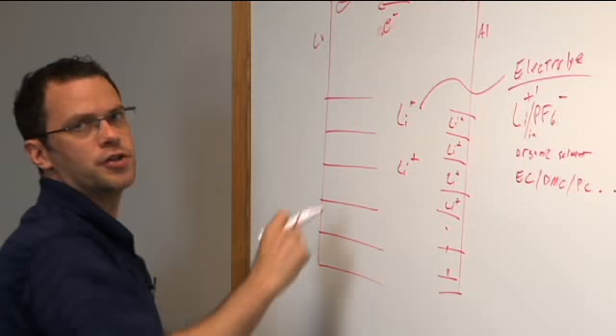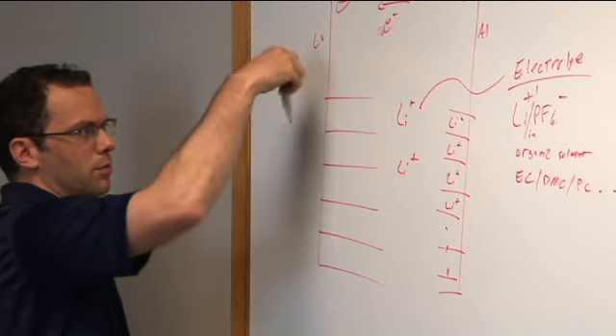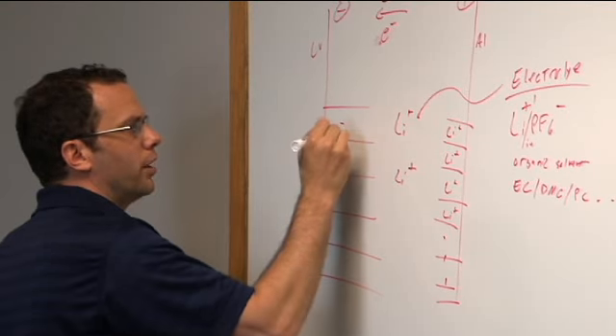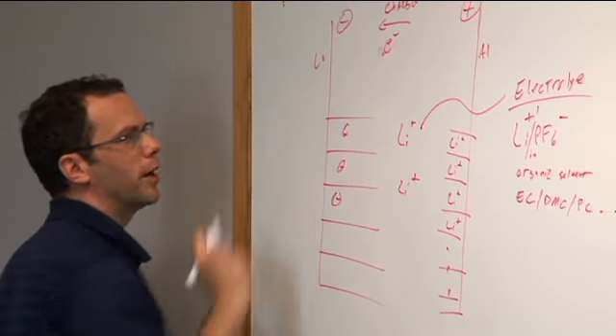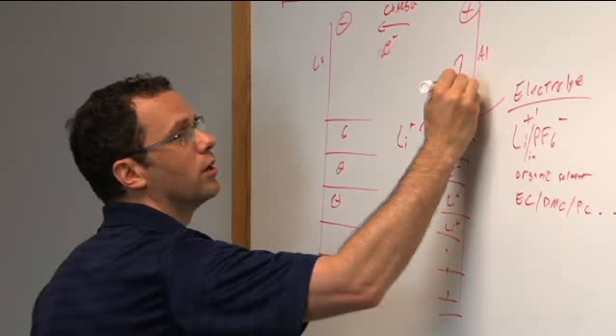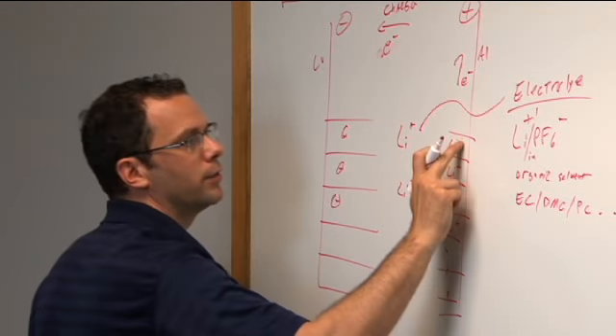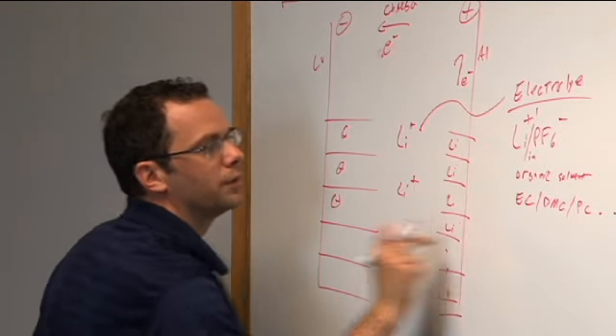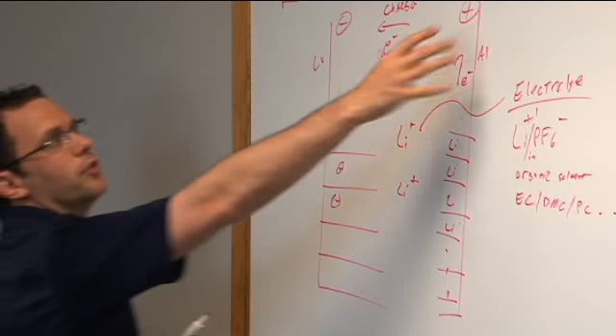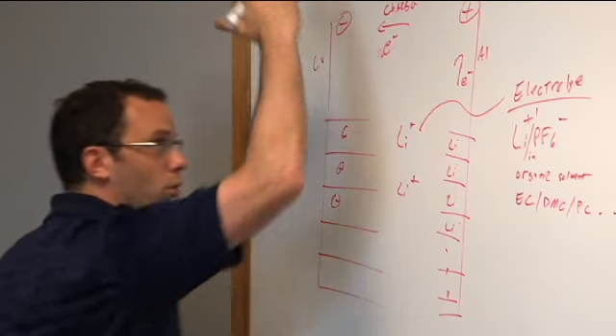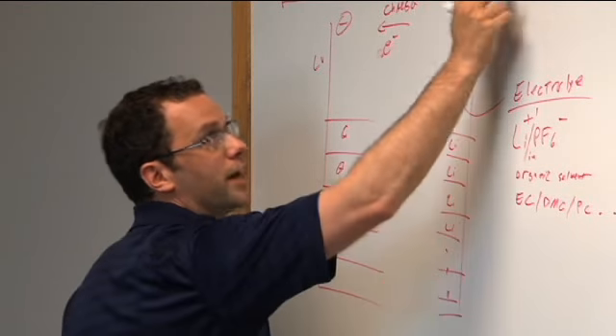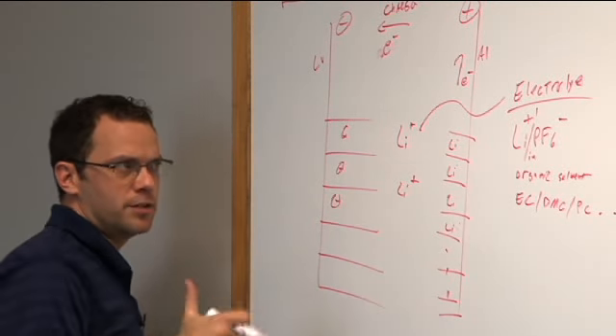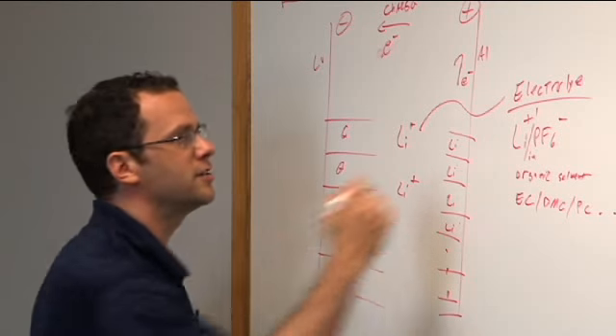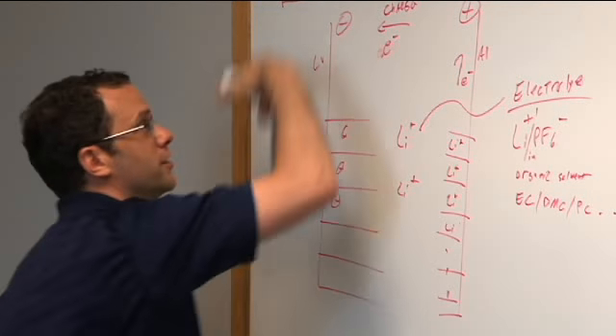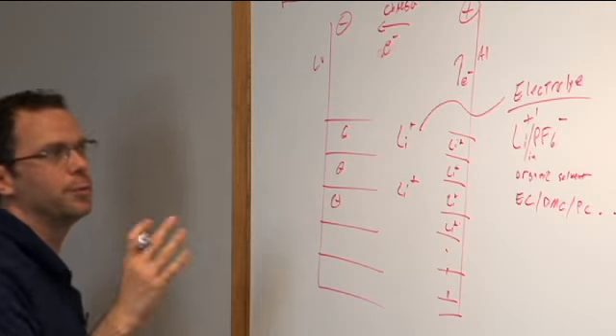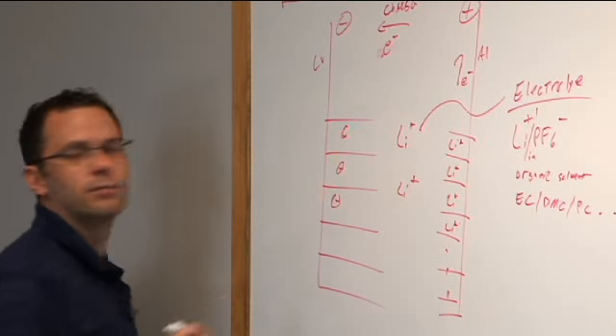And now I'm going to charge it, which means I'm going to force electrons down into my anode. When I do that, I build up local negative charge, right? And at the same time, I am stripping electrons from my lithium iron phosphate. The lithiums actually are not ions, as I said, inside my lithium iron phosphate. But when I pull a current from it, I am pulling electrons out of this material. And it turns out that the person with the short stick is a lithium. And it ends up becoming ionized. So these electrons, as I charge, are actually ultimately coming from where the lithium is in the system.